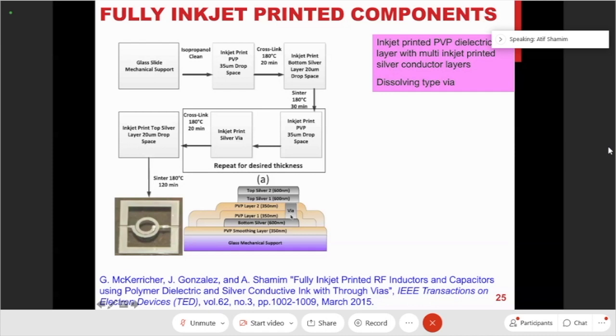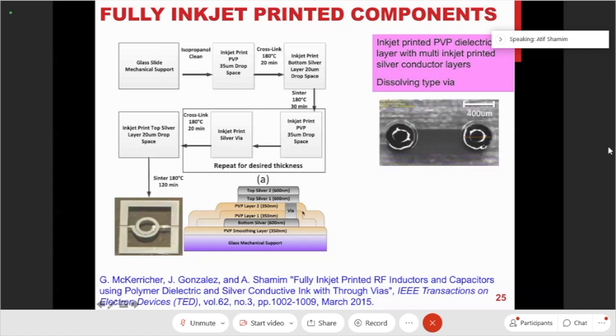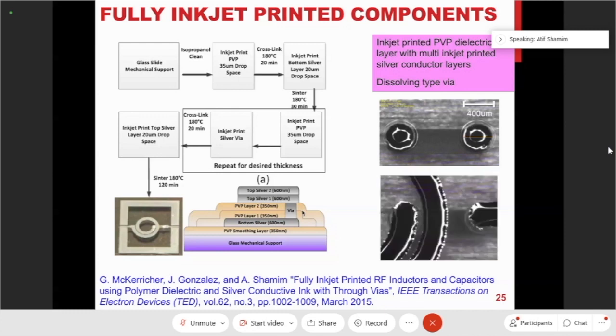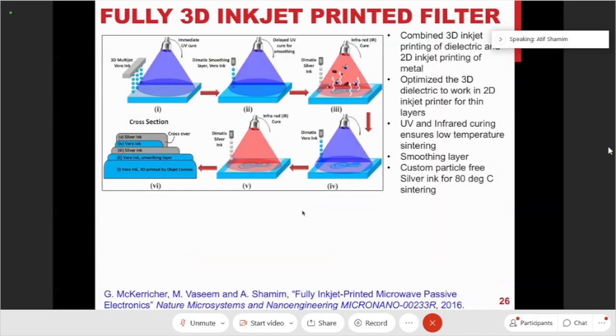These vias were interesting. We called them dissolving type vias because here we did not use lasers or anything, since these were thin layers. When we printed the dielectric layer, we did not heat or sinter it, so it was still wet, and we printed the metal where the via was supposed to be. So the metal connection was made, and then we would heat it, and no more metal can penetrate through. So we call these very interesting dissolving kind of vias.